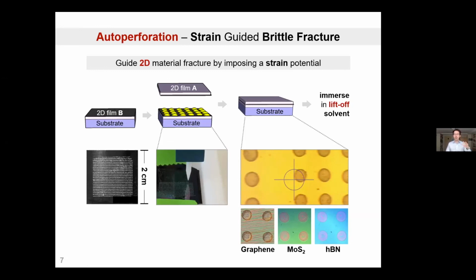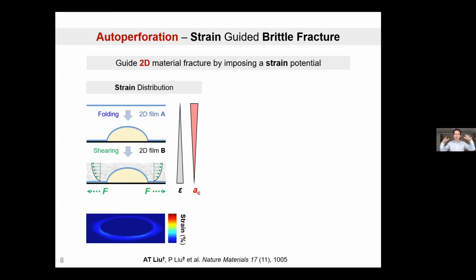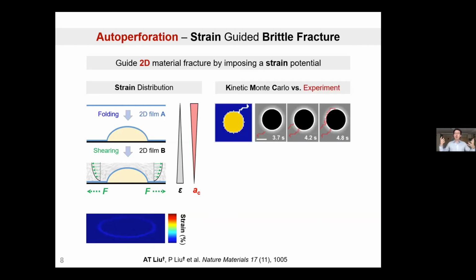So what would happen if you put this whole thing inside a lift-off solvent to erode away all the polymeric support for these 2D materials? If you think on the scale of a single layer of 2D material folding over one particle, as this layer folds over the polymeric pillar that we have previously printed, you naturally form this ring of maximum hoop strain. This is very similar to folding a piece of tablecloth over a circularly shaped table. You're naturally going to get maximum strain on the edge of the table, right? According to Griffith theory, this ring of maximum hoop strain can be used to attract a randomly generated crack within the material, and the crack will propagate along this ring.